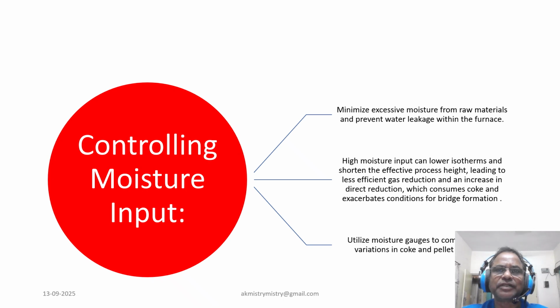Because many times if it gives a wrong signal, with uncalibrated gauges, then we may be deceived by the values getting displayed on the gauges, and we may not have precautionary corrections, or our precautionary correction may be delayed, for which we may have to pay a lot of penalty in terms of coke rate, abnormal furnace behavior, hang and slip situations, and so many things. So by diligently applying this multifaceted strategy, we can effectively manage and mitigate excessive delta P, ensuring a stable and efficient blast.